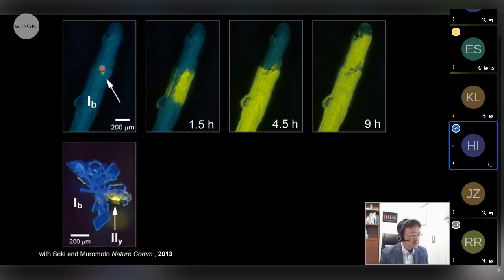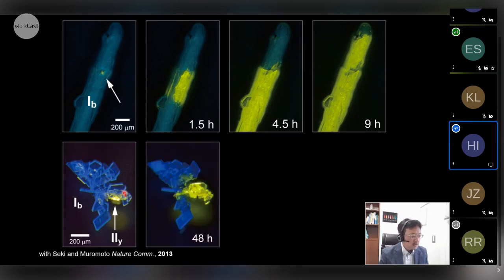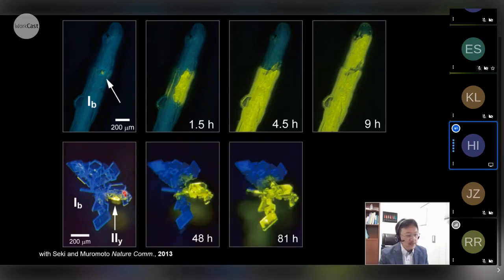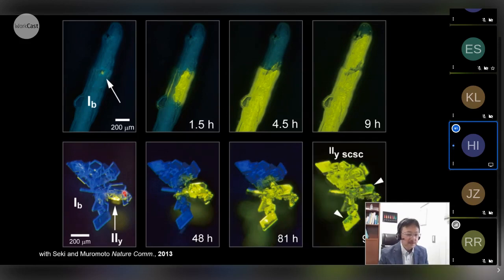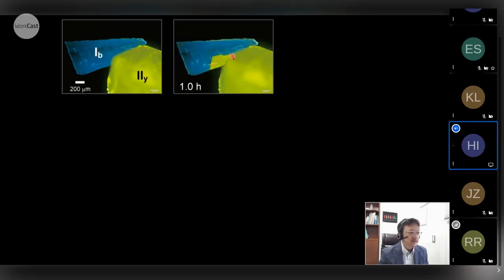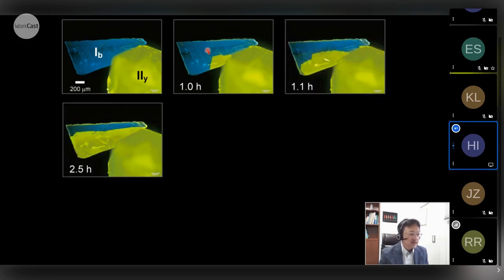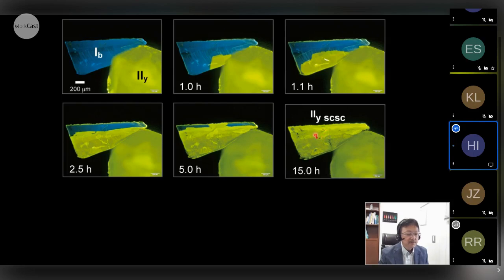The other interesting thing is that if you make a similar yellow spot on a group of crystals, this phase change can develop across the boundary of the crystals. This is very interesting, and other crystals that were not in contact with the yellow part did not change. This yellow color change was induced just by contact with the yellow phase. So then we did another experiment. We put the yellow crystals onto the blue crystal. After 1 hour, a new yellow phase emerged on the surface of the blue crystals, and this phase automatically, self-replicatively developed through the entire blue crystal.